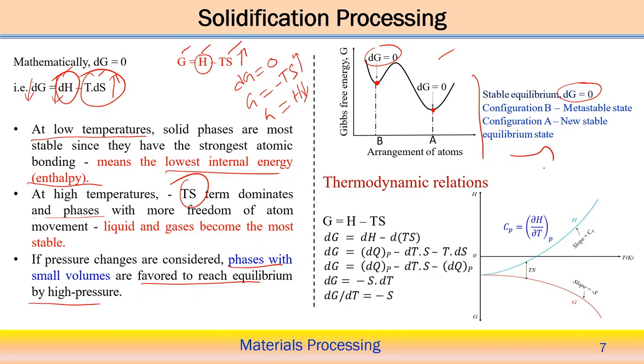So now overall we can look back at the thermodynamic relations to relate the enthalpy H and the Gibbs energy of a system, and see how to represent them graphically. The x axis represents the temperature, and on the y axis, the positive side is the enthalpy, and the negative side indicates the Gibbs energy. So we start from here. This curve represents the enthalpy of the system as a function of temperature, and this curve represents the Gibbs free energy of the system.